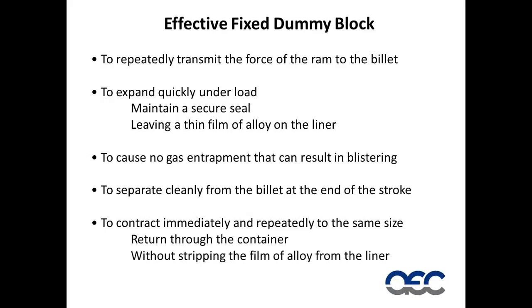We would like the rate of expansion of the dummy block to equal the upset rate of the billet, in which case we can eliminate any gas entrapment between the billet and the liner. We also need the dummy block to separate from the billet at the end of the stroke so we don't cause any downtime discarding the butt. Prior to the dummy block coming back through the liner, it needs to contract immediately back to its original size and come back through the container without stripping any aluminum from the ID of the liner.